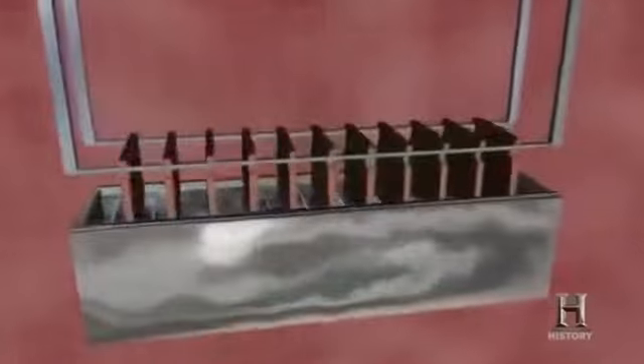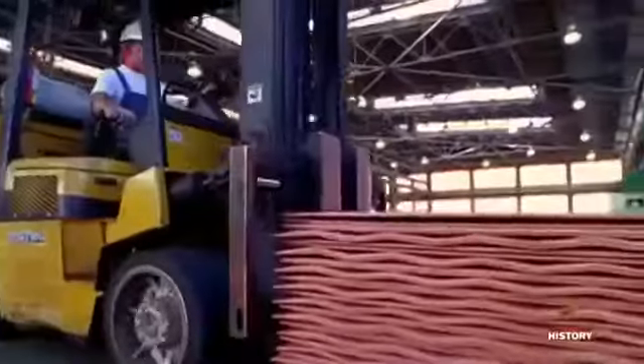Racks of anodes are lowered into an acid solution interlaced with stainless steel cathodes. For 10 days, an electric current passes between anode and cathode, causing copper ions to dissolve off the anode and redeposit on the cathode as 99.99% pure. 1 ton of ore from the mine has yielded 12 pounds of refined copper.